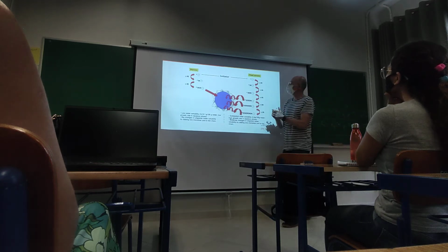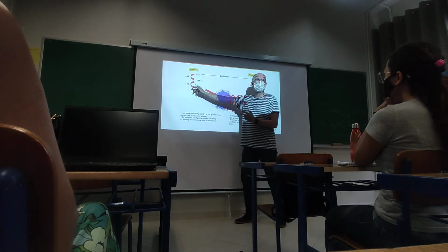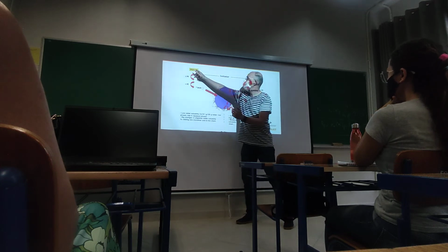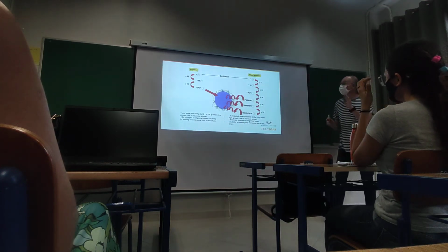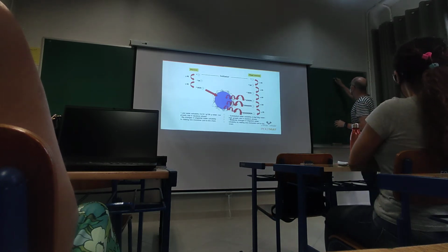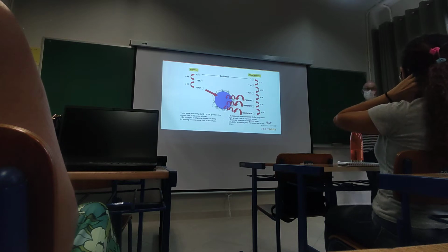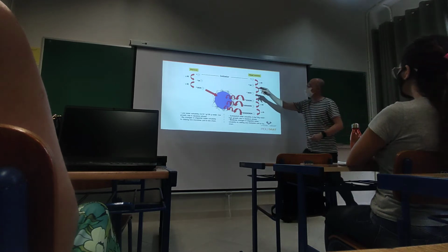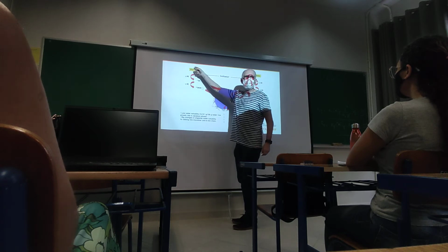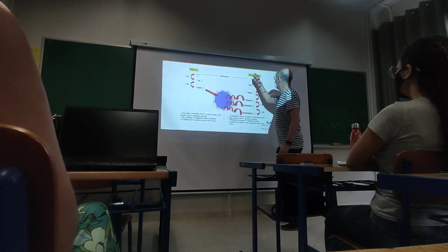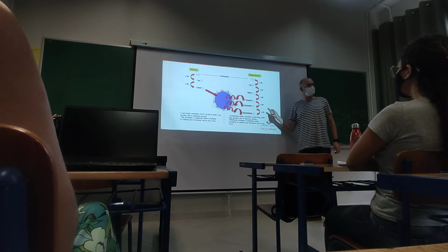So this means that the polymerization rate in the aqueous phase with styrene for this addition will be really slow, because the concentration of monomer in the aqueous phase will be very low for styrene and high for vinyl acetate. So the addition of monomer units in the styrene polymerization will go slowly. For vinyl acetate it will go fast.